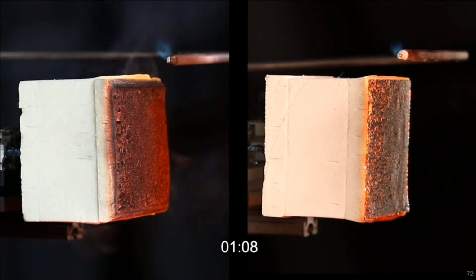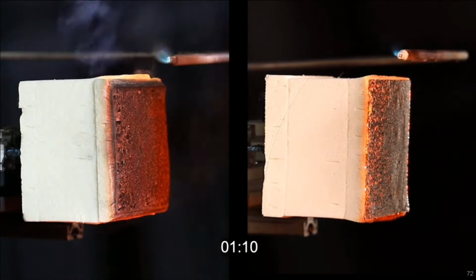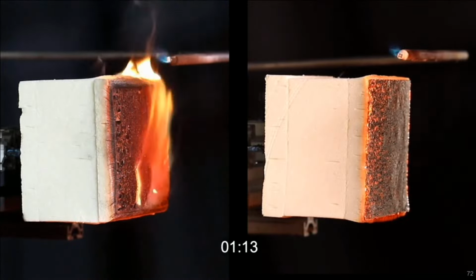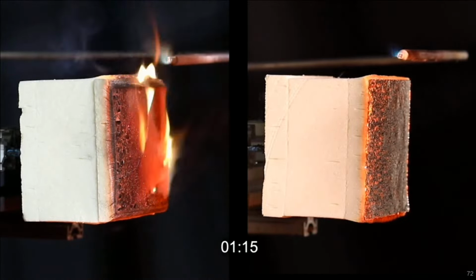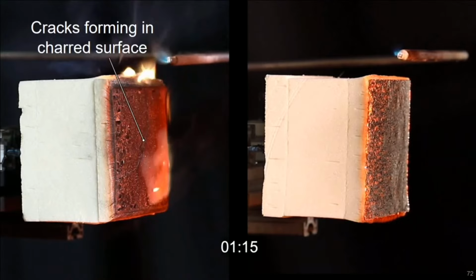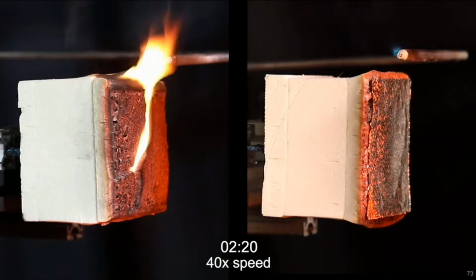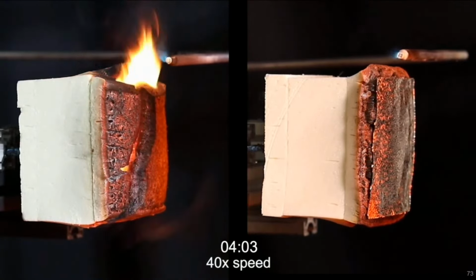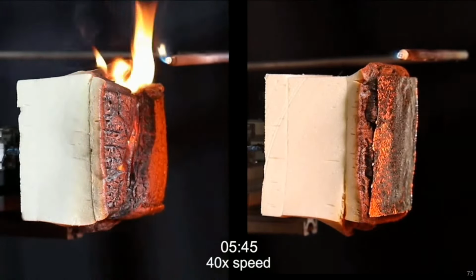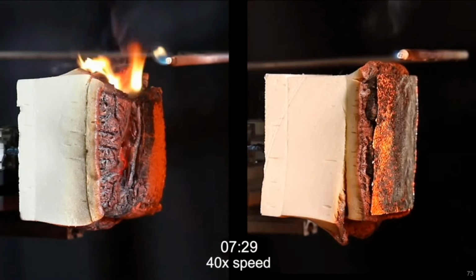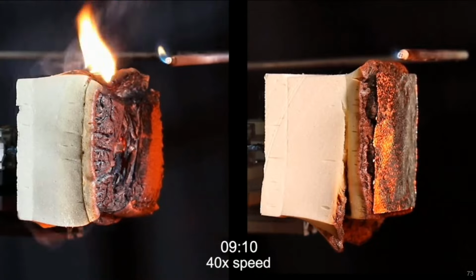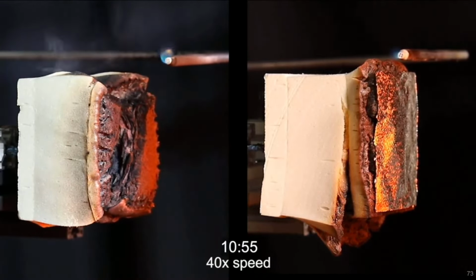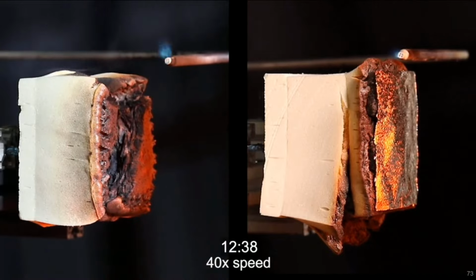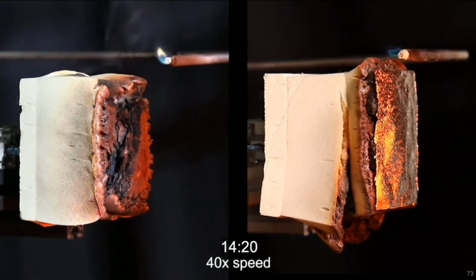So there you can start to see the formation of a crack in the front face of the char in the left-hand video. So there's cracks formed in the char surface, and flaming then persists for several minutes. Now I'm going to let the video run at 40 times the normal speed, because these are 20-minute long tests. And we can see that the sample, which is protected by a foil facer, doesn't ignite at all during the course of an otherwise identical experiment, whereas the unprotected sample is gradually consumed as it runs forward.